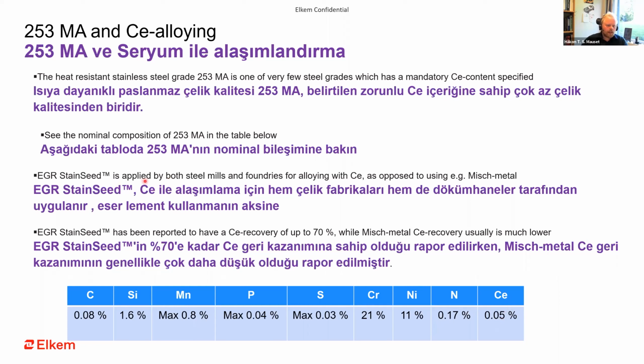But our EGR Stainseed is supplied to both steel mills and foundries for alloying with cerium instead of using mischmetal. I think a lot of the steel mills and foundries that make these grades use mischmetal, and then they get a lot of lanthanum as well. But we have several customers who use our Stainseed as a cerium alloying agent, not for grain refining, but for cerium alloying. And one of the reasons is that our Stainseed has a cerium recovery of up to 70% of the cerium, while mischmetal cerium recovery usually is much lower. I don't have any specific numbers myself, but I've heard 10 to 30% recovery. And of course, mischmetal is also very reactive when you put it into steel. There is a lot of light and smoke and such, while adding EGR Stainseed, nothing is happening. There is no reactivity.